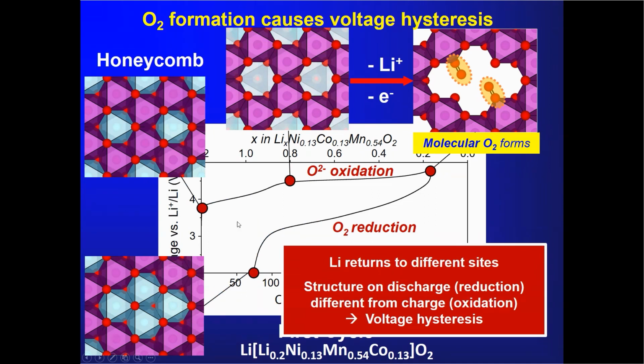But the message here is that you can weaken metal oxygen bonds, form the molecular oxygen that we see evidence of in RIXS. I should say we've also carried out oxygen-17 NMR, which also identifies molecular oxygen in the structure and indeed allows its quantification, and that matches well with the charge capacity on this plateau.